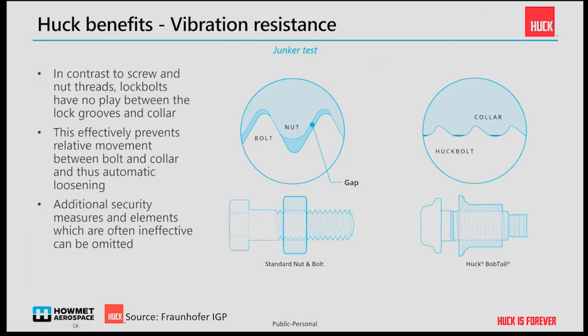Here we can again see the biggest difference of a conventional thread to a Lockbolt. On the right-hand side, we see the collar swaged into the lock groove. So this leaves no room between the pin and the collar. And this assures the vibration resistance of our fasteners and also the high consistency of the preload. With a conventional nut and bolt, you always see a certain gap which allows the assembly of the nut, and this all results, under high vibration loads or fatigue loads, in self-loosening of the nut and bolt in extreme cases.